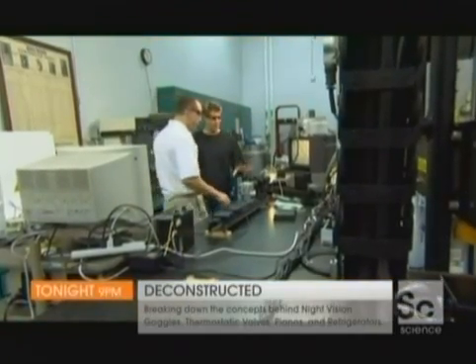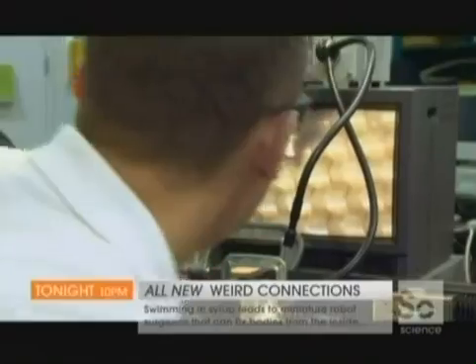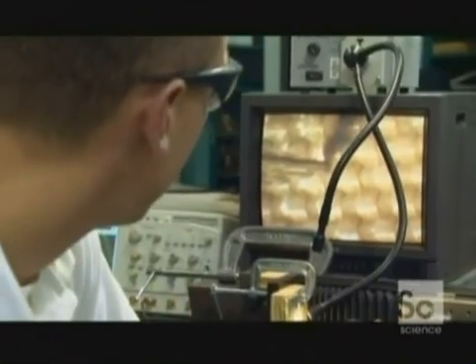Now let's see why. Eric put the Kevlar swatch under a microscope. Pretty good in focus — you can see how the spike pushes around the tough fibers; it just slides right between them. So no matter how tough the fibers are, a sharp blade can just slip through.